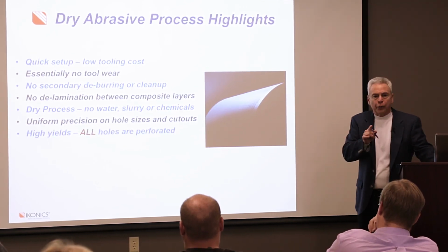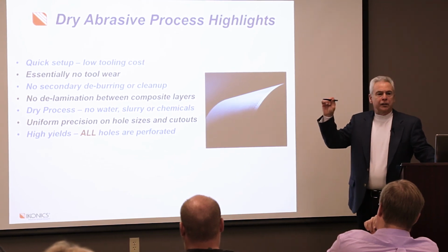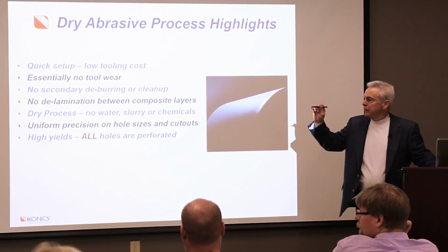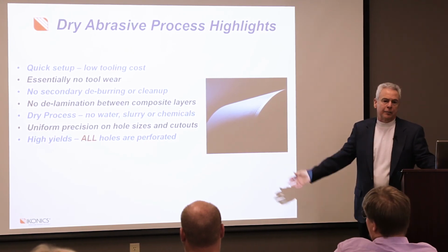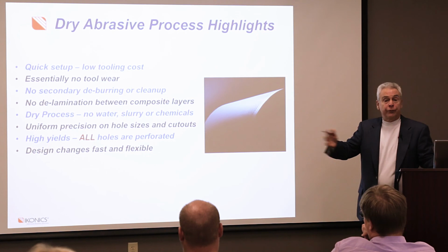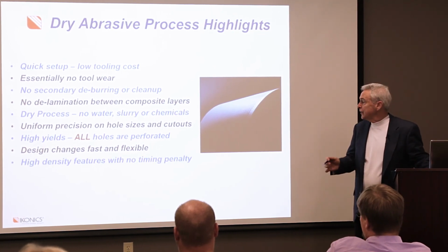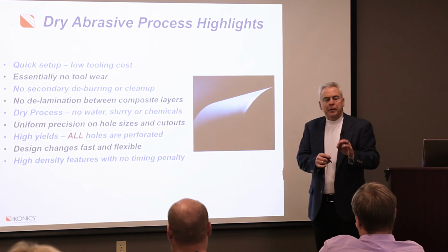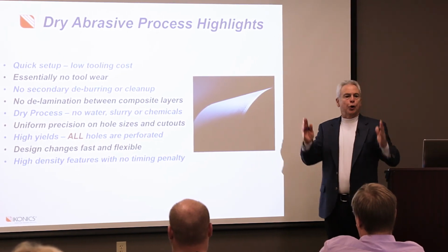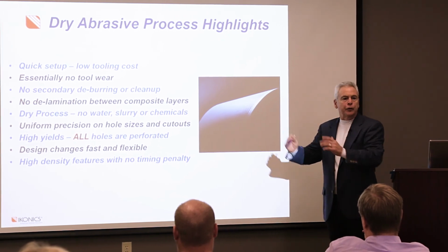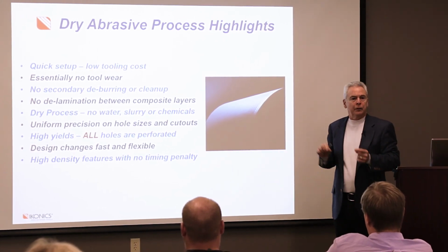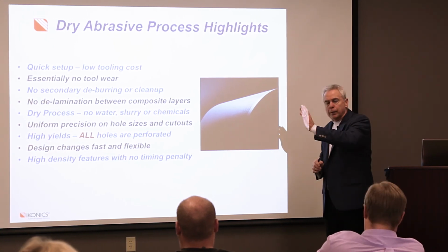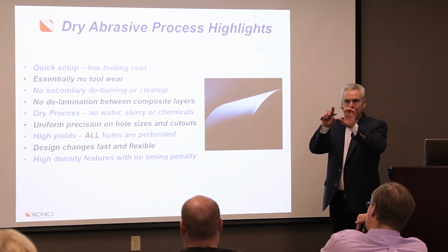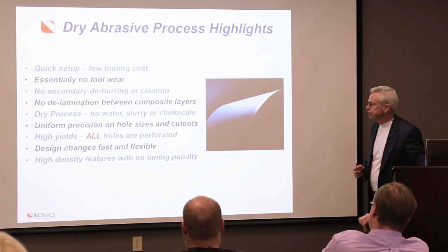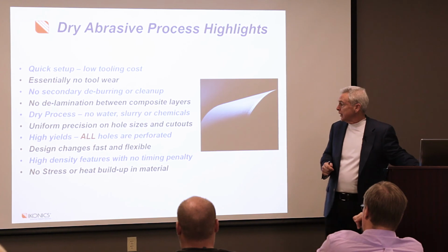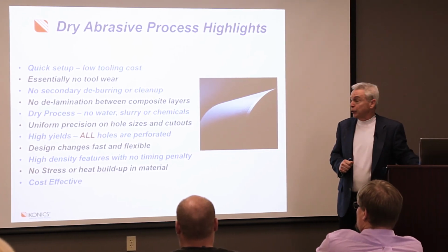High yields. All the holes are perforated. You're not going through drilling one at a time where you might have a broken drill bit and miss a hole. It doesn't happen with this process because they're all being done at the same time. Design changes are fast and flexible. We just mentioned that. High density features with no timing penalty. What does that mean? If I had a panel that had 100 holes in it, or another panel that had 1,000 holes in it, and I needed to perforate both of those panels, the time to do it is the same. Because of the way the process scans, it's defined by how many holes are in the photoresist. No stresses or heat buildup on the material, and it's a cost-effective process.